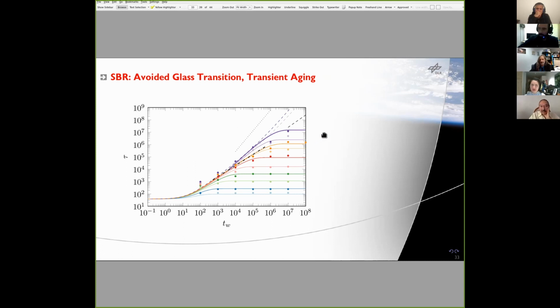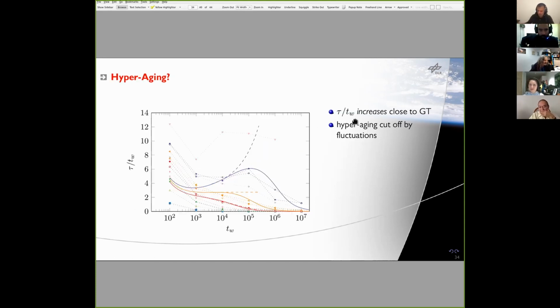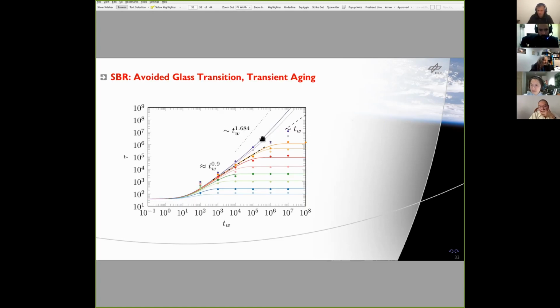And of course, since including fluctuations smears out the glass transition, there is no true divergence of the relaxation time anymore. And therefore, in all cases, we finally approach a waiting time independent stationary state. So if you see this, you could think that maybe this prediction of faster than waiting time aging was kind of fancy and nice. And I quite liked it when I first saw that this comes out of MCT. But apparently it's not really seen in real life.